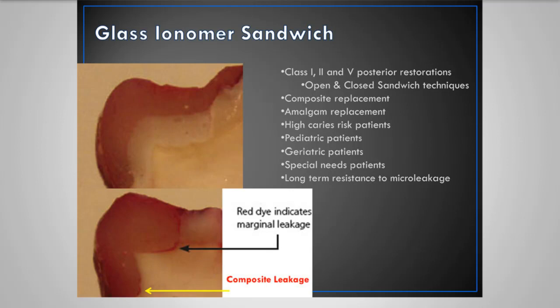Again, that can be from polymerization stress, maybe not having a good bonding agent technique, or maybe the bonding agent was torn from the tooth structure because of the stresses involved, or maybe the bonding agent itself isn't heavily filled to get good strength properties, or maybe it's just technique. There's a lot of different problems that can arise. Now, in looking at the dye penetration on this particular one, what I want you to see with the glass ionomer sandwich technique is the glass ionomer does not show the microleakage problem that you find with traditional composite modalities. And we know composites absorb moisture.